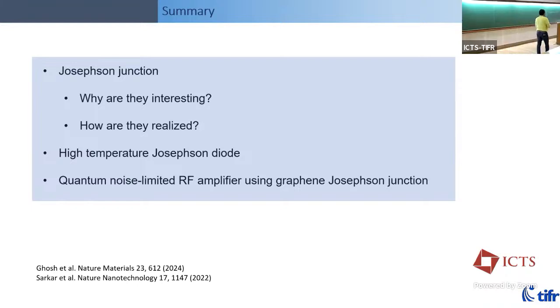Mandar, what stopped you from doing the Shapiro steps in the first part? Nothing stopped us. I don't think personally it's a way to measure the current phase relationship, but there are ways to measure the current phase relationship directly, which is what we are doing. Shapiro steps is one way to show that you have higher order harmonic components. That's all. So it's not a measurement of the current phase relationship. You just didn't do it? No, we were actually more interested in trying to directly measure the current phase, which is still our interest. Because the Shapiro steps measurement is not smoking gun evidence. It's an indirect statement that there could be some higher order components.